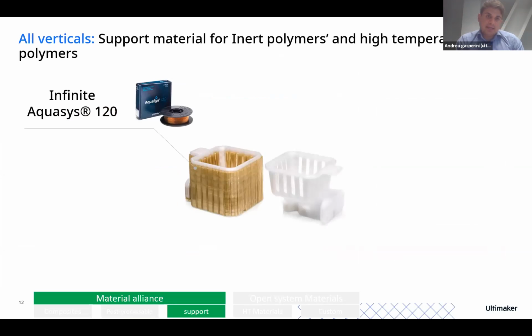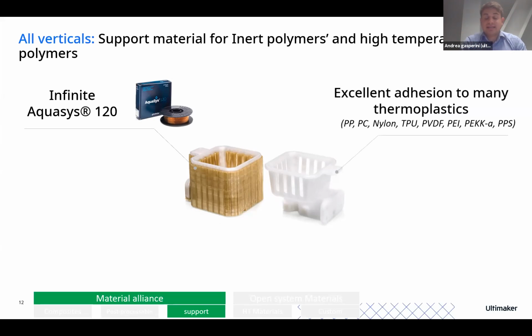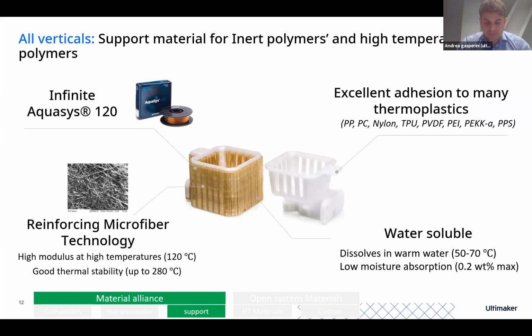Then the second part here is I want to talk to you about a new material that came out last year. It's basically the complementary support material for PVA. So we know that PVA is a really good support material for thermoplastic material, but it has certain limitations. Therefore, Aquasys 120 is really covering that limitation by being able to use this material as support for inert polymers. So I'm talking about the polyolefins of this world. I'm talking about polycarbonate, PVDF, and all the high temperature polymers, because this material has a pretty good high temperature resistance. Indeed, it has a pretty high storage modulus at high temperature, around 120 in a heated chamber, but also up to 280 as well when it comes to extrusion.